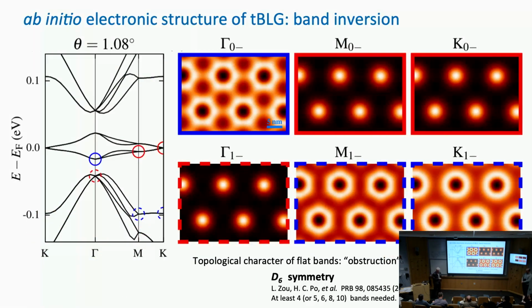This was realized very early on. There are several very nice, beautiful theoretical papers written about this, one from my colleague at Harvard, Ashvin Vishwanath, and they called this obstruction and fragile topology. Basically, they were trying to say with these words that if you go from gamma to a different region, you find a very different character, and you get this crossing. So that's what obstruction and fragile topology meant to capture.